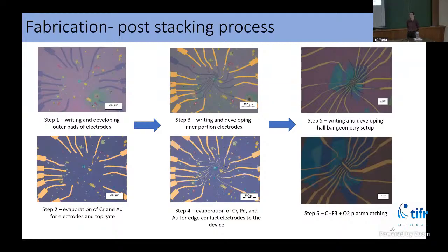How long does it take, from the day you start to the final device? Conservatively speaking, 2 weeks, from the moment I get a flake to the final device. Getting the flake itself can also be challenging because that depends on luck and the stochasticity of whether you get a monolayer flake large enough to cut into 3 pieces. That requires a certain amount of skill as well. So once those things are overcome, this can be done in 2 weeks.